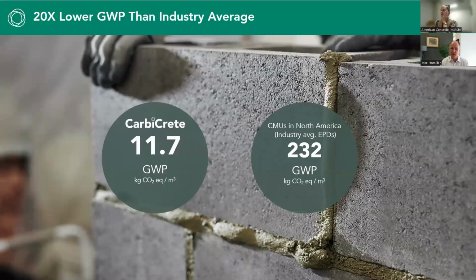To give you a frame of reference, we have a third party produced and ASTM validated EPD. But I think one of the key takeaways is if we look at the global warming potential of a CarbiCrete material, we generate about 11.7 kilograms of CO2 per cubic meter of concrete. When we compare that to the industry average in North America of 232, we're about 20 times lower in GWP than the industry average, which is really a significant impact on the CO2 attributes of concrete and makes it a much more impactful, low carbon building material for industry.